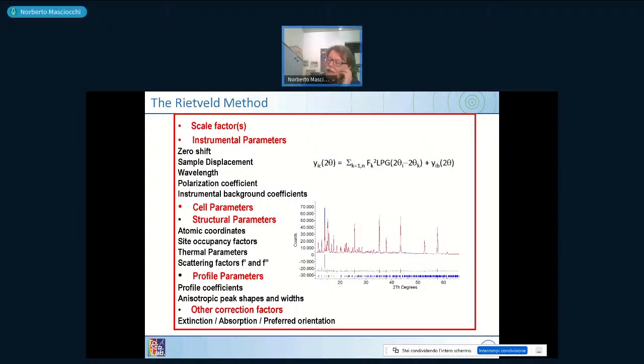The important thing is that in single crystal diffraction, you don't have instrumental parameters because you measure directly the intensity of each separated spot. The cell parameters are determined beforehand and are not touched anymore during refinement. The structure parameters are those of your interest, and there are no profile parameters and no other correction factors. That means that a single crystal uses a subset of parameters. It is easy from the mathematical point of view, and the number of observations is much larger, because there are tens of thousands of data which can be measured.